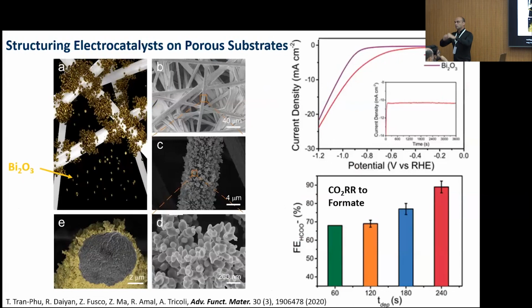We can also deposit on porous substrate. This is a carbon fiber paper. And here we deposit bismuth nanoparticles, bismuth oxide, which are good for another catalytic purpose. So CO2 electroreduction, in this case, to formate. So you can actually make catalysts for a variety of issues.